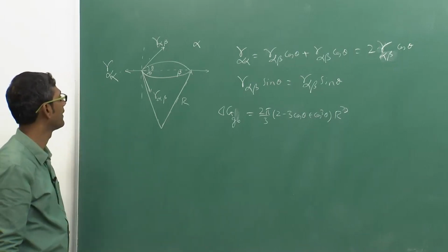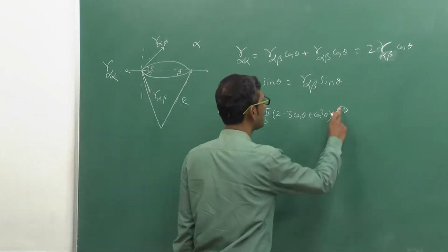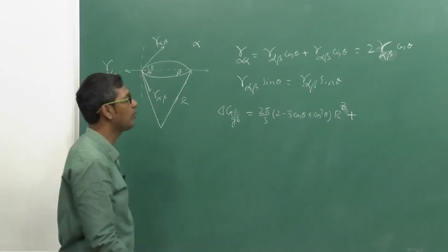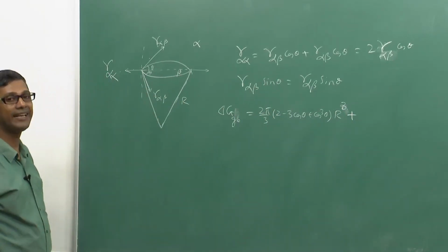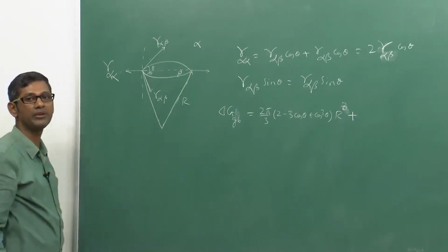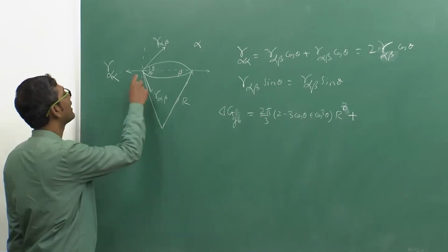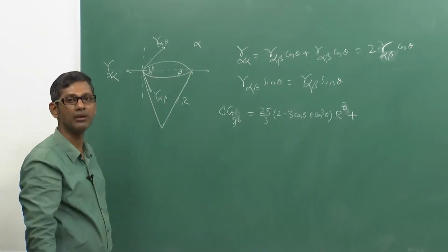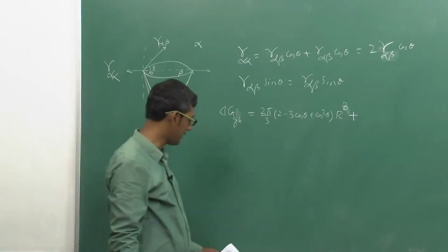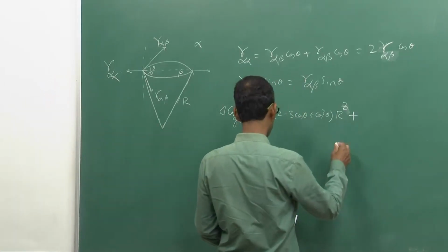Same way, I can draw a virtual sphere. Correct. So now what is the loss of energy and what is the gain of energy? Obviously the loss of energy is these two interfaces created between alpha and beta, and the gain is that the earlier grain boundary is now recovered. The earlier grain boundary between alpha alpha is now recovered. That's the gain. So let us write down that.